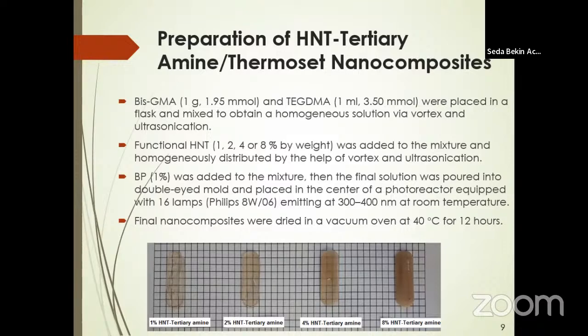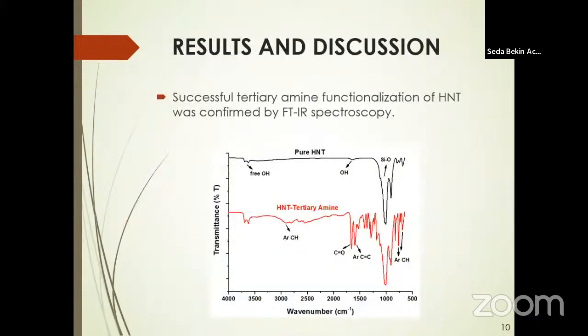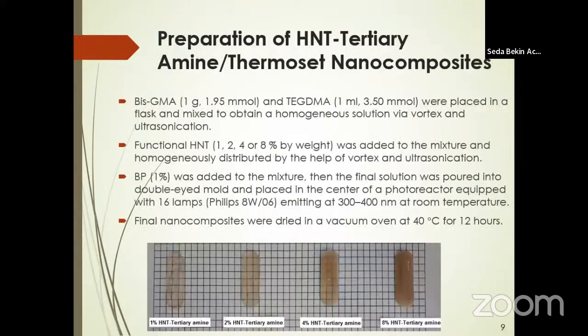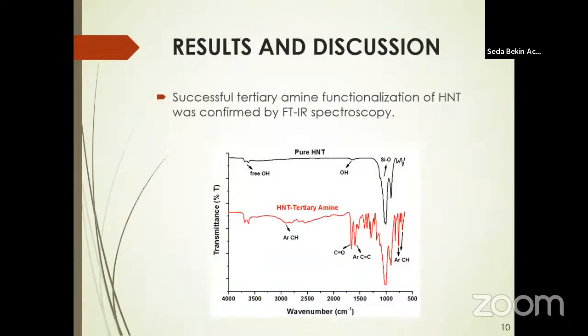Benzophenone was added to the solution mixture, and thermoset nanocomposites were obtained in a photoreactor with 16 lamps emitting at 300 to 400 nanometers at room temperature. Final nanocomposites were dried in a vacuum oven at 40 degrees Celsius for 12 hours, and all other polymerizations were performed under identical experimental conditions, and the resulting nanocomposites are as shown in the figure.